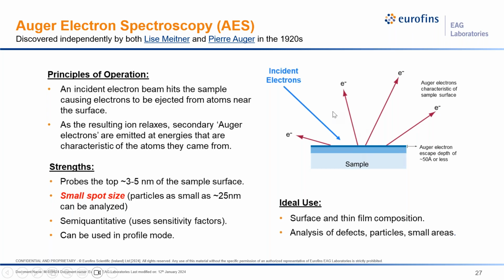But for Auger, we start out with an incident electron beam striking the surface, and we are going to be collecting the Auger electrons that are emitted from the surface. AES operates similar to an SEM. We can do backscattered secondary electrons. We can also put an EDX detector on there as well. The important thing to note, though, is that for this technique, XPS and ToF-SIMS, only those electrons and the secondaries that escape the solid surface can be detected, and that gives us our thin film sampling depth resolution.